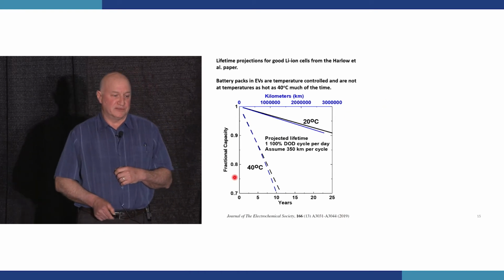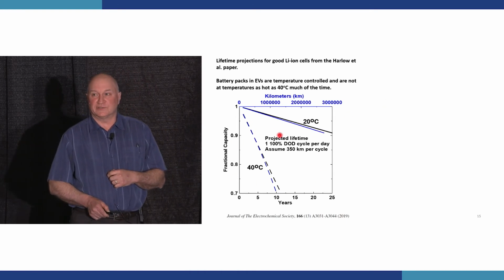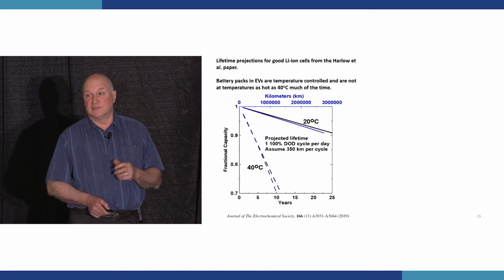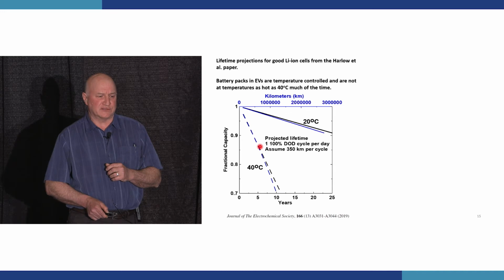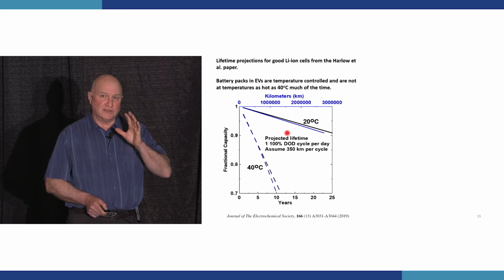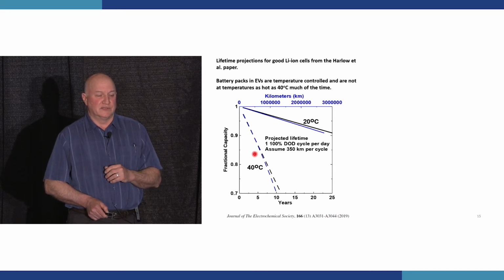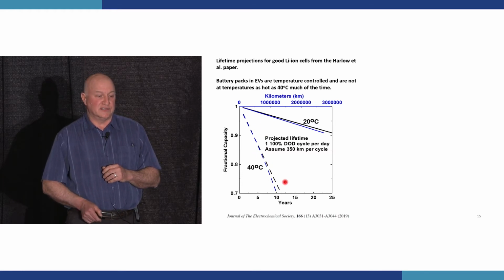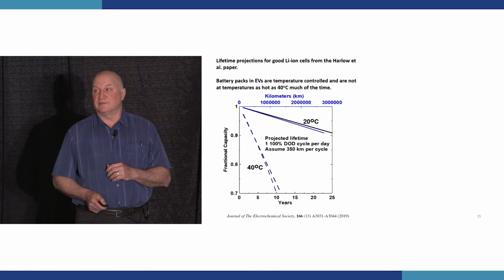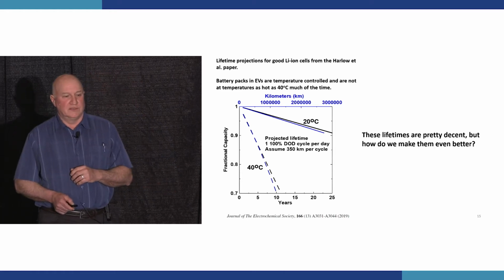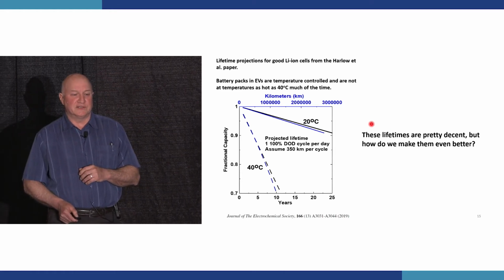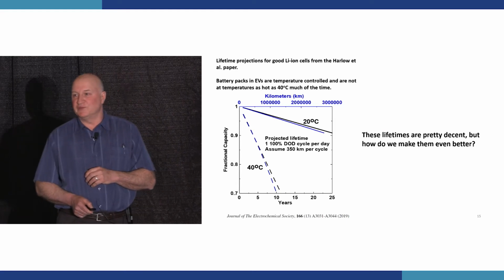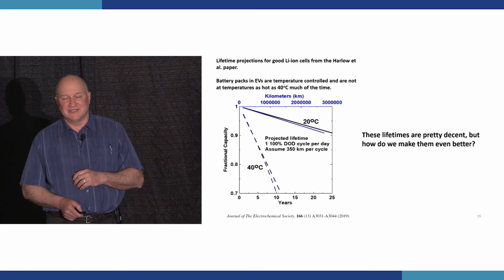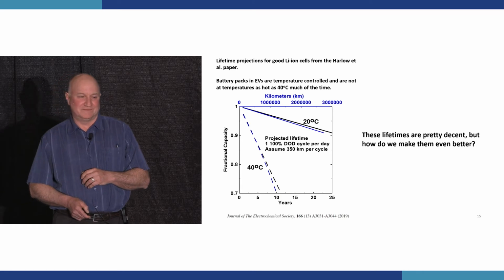And lithium-ion batteries degrade more rapidly at higher temperature. This is because there's unwanted parasitic reactions that occur between the charged electrode materials and the electrolyte. Very small, but they accelerate with temperature. So at 40 degrees C, you're basically looking at 10 years of life till 70%. So these lifetimes are pretty decent, but how do we make them even better? And that's what I want to talk about today.